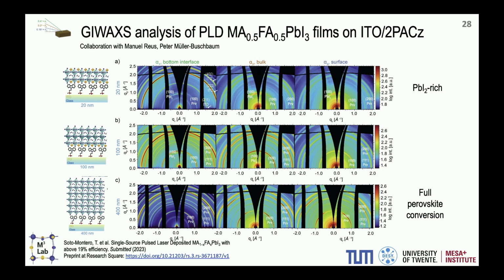So when we have a thin layer on the substrate, which is ITO with SAMs, you have mainly lead iodide. We can see it actually very clearly there. So it seems that we ablate everything from the target, but only the inorganic attaches to the substrate first. So it seems to be something related with the sticking on the substrate. So here it is lead iodide rich, but as you increase the thickness up to 400 nanometers, then the whole perovskite starts forming. So it seems to be kind of a two-step process, very similar to co-evaporation. We ablate the material in a different way, but the growth of the film is actually very similar. So above 400 nanometers, we have the full perovskite conversion.